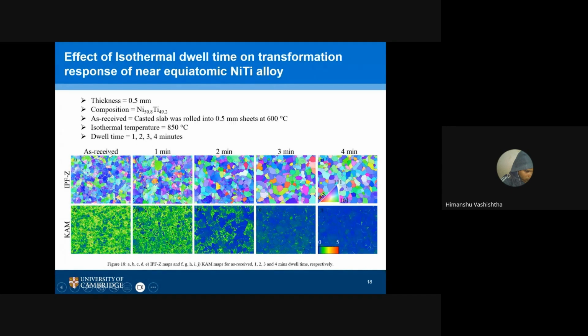So in the as-received condition, too many white lines are there, meaning too much deformation was present. To convert a slab of NiTi to a sheet, we have to roll it, and during the rolling, a lot of deformation has been accumulated. You can see this in the form of KAM maps, reaching a lot of green or even yellowish range.